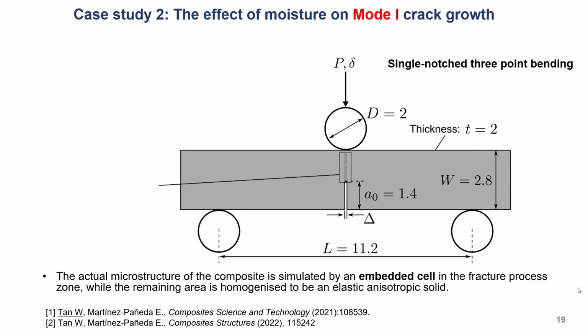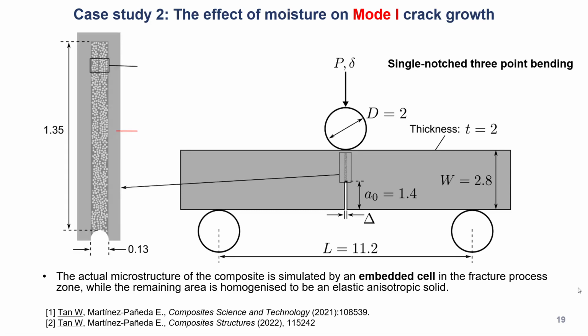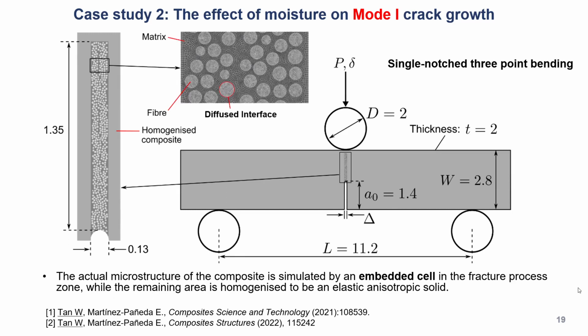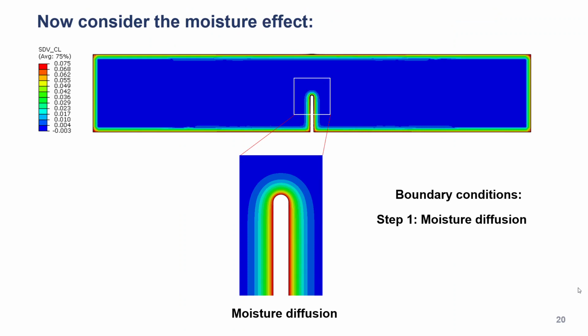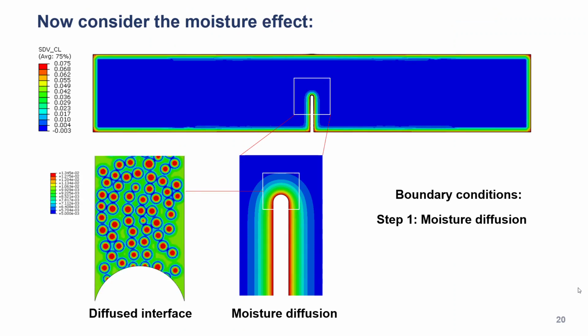Let's look at case study 2, how we model the influence of the moisture on the mode 1 crack growth. This is the virtual single edge notch bending test, where we want to predict the fracture toughness in the mode 1 case. To model this at the microscale, we use an embedded zone. Ahead of the crack tip, we use a small window where we can put the tiny fibers and matrix in a random manner, and then we can model their interface as well. This simplifies the problem because outside that embedded zone you have all homogenized properties. Then we can apply the moisture boundary and consider the diffuse interface. Then apply the second step, mechanical loading here.